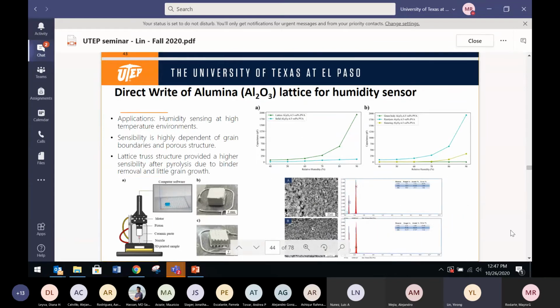Okay, so this is another interesting application. We were able to print alumina and control the lattice structures, so therefore we can use it for humidity sensors. The higher the surface area, like I said, the higher sensitivity it'll have. So basically, you can print a humidity sensor based on lattice design using 3D printing.